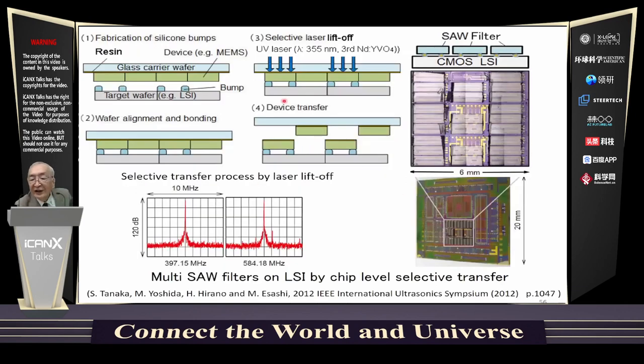The other heterogeneous integration method is chip level selective transfer. This method is required in case the size of the MEMS chip is different from that of the LSI chip. A selective transfer process called laser liftoff or debonding is used, as shown in upper right. In this method, by irradiating the acrylic resin using a UV laser through a glass carrier wafer, the resin is carbonized to lose adhesion, and the FBAR chip is transferred to the surface of the LSI wafer.